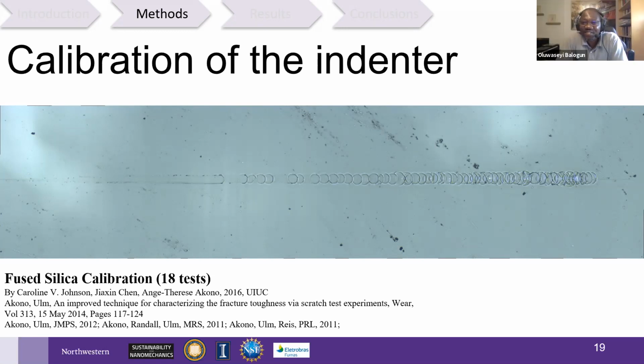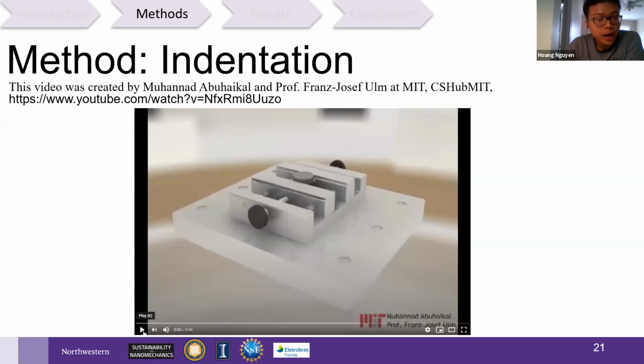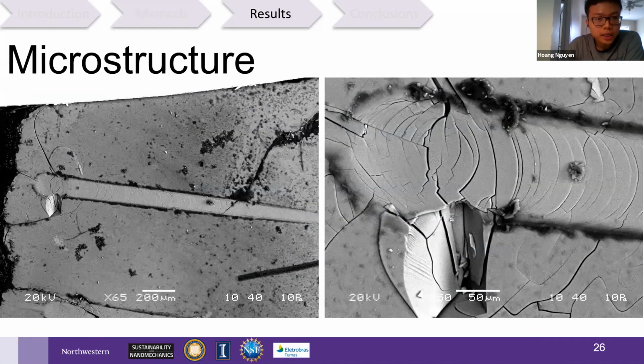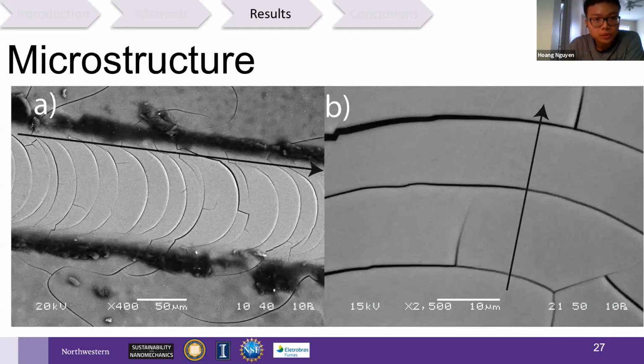So from my understanding of the talk, the fracture energy comes from the surface that you created when you scratch away the material, right? And also from the SEM image, there's some subsurface cracking. In the calculation, do you have to consider the crack length of those subsurface cracks that you created? Because that must dissipate part of the energy, right?